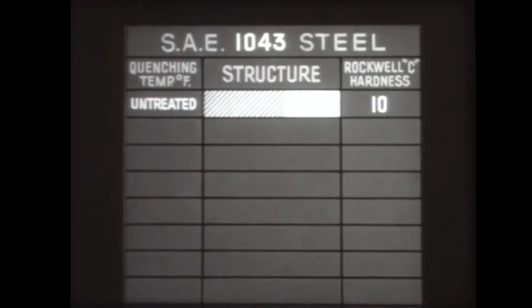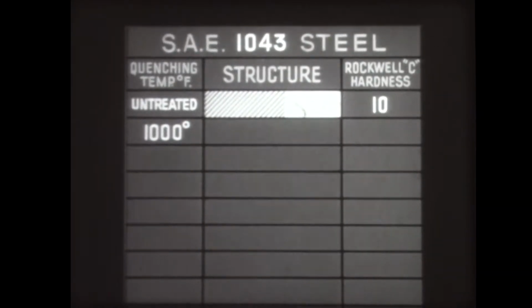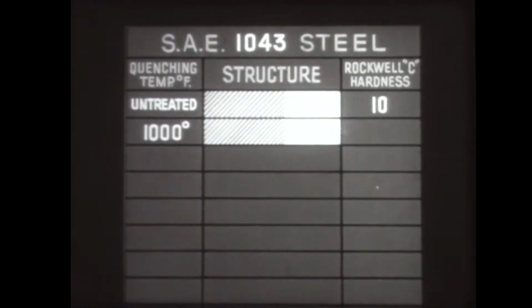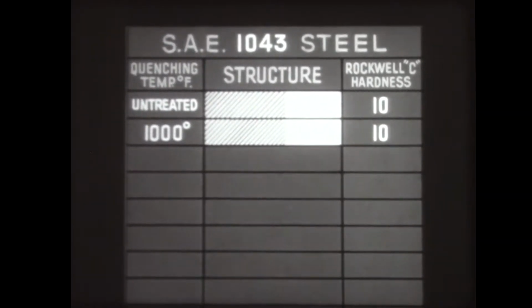Now assume that the steel is heated in a furnace to, say, 1,000 degrees Fahrenheit and quenched in water. A micrograph of the steel at that stage shows that no structural change has taken place. So we record that when quenched from 1,000 degrees, the structure remains unchanged. A Rockwell C test would show that the hardness remains at 10. In fact, no change occurs until the steel is heated to 1,320 degrees and quenched.